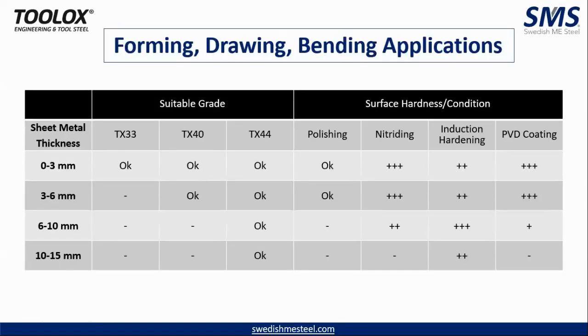Okay, so this chart gives you an idea for forming, drawing, and bending applications. This chart just gives you a guide. It has been taken from various applications that we have developed from across the globe. What it says is if your sheet metal thickness is 0 to 6 mm, in most of the cases nitriding is more than sufficient. If you want better life than that, then you can go for PVD. But as a whole, Toolox 44 plus nitriding should hold true for 0 to 6 mm.